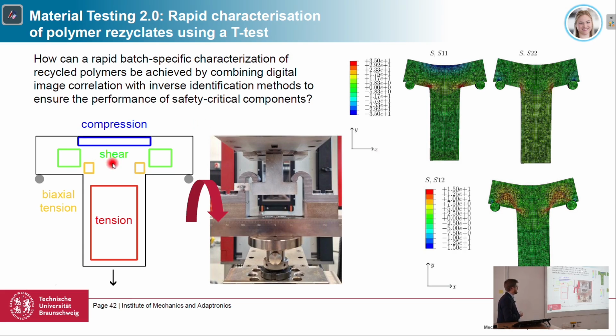And we started with a test called T-test, which has boundary conditions left and right, and here you apply a tension load, and then in this T-shaped test specimen you get different regions. Here is a tension region, here above a compression region, we have a shear region, and also biaxial tension. So you can get tension and compression properties, at first hand stiffnesses, so Young's modulus, and you can get shear values. And with the material under investigation, again PP, we performed finite element simulations of these tests, and we also saw the different regions for compression, for tension, and for shear, like assumed when designing the specimen.